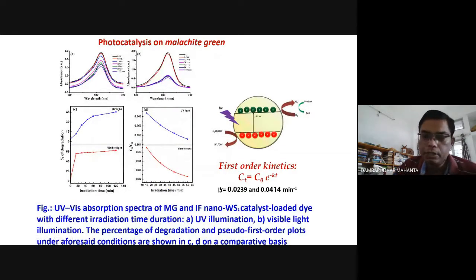So we used these materials, called inorganic fullerene type WS2, for targeting malachite green. Malachite green is a pollutant, and it is used for preserving sea animals, seafoods in fact, and it is very hazardous to the environment, so people would like to degrade this material when it is available in excess. What is interesting here is that photocatalysis is a study in which we excite electrons from the valence band to the conduction band, and in that process a redox reaction takes place, and generally we apply first order kinetics and see how much degradation has taken place.